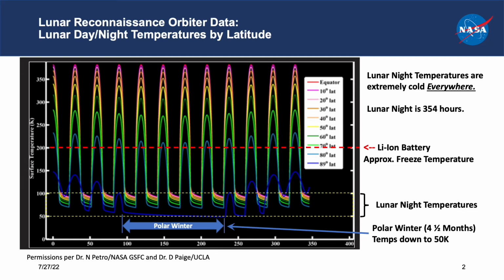The red line in the middle of the chart at around 200 K is basically where we expect the lithium-ion batteries to freeze. Below that, you get into the lunar night temperatures. It typically ranges between 50 and 100 K. And further, in the polar regions, this 354 hours now becomes instead 4.5 months, where a polar winter will take the temperatures down to 50 K.